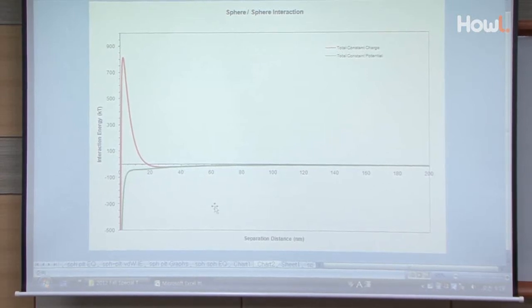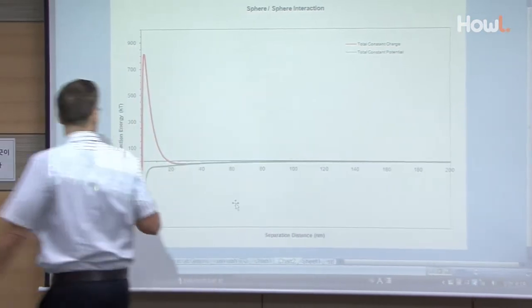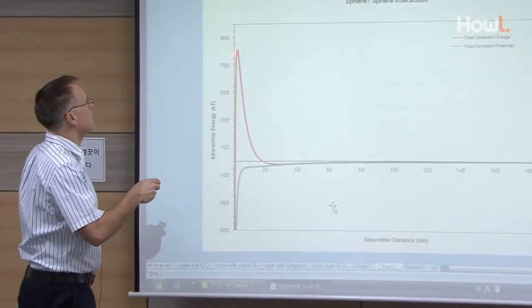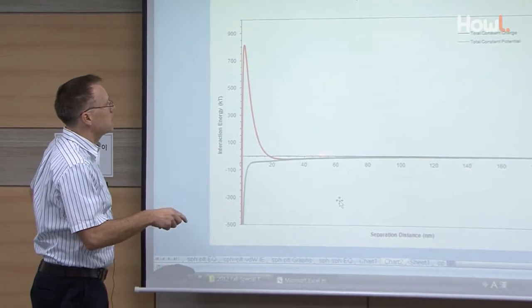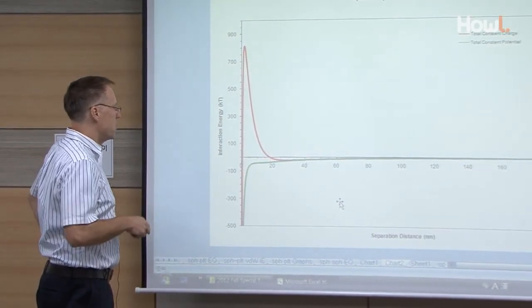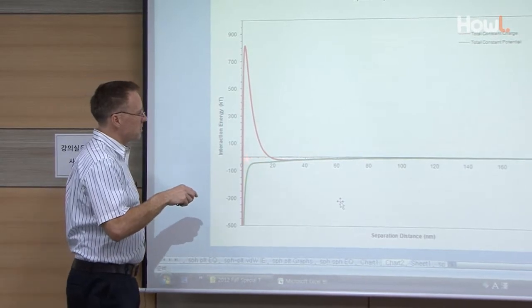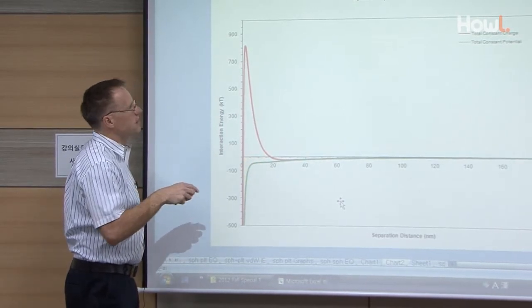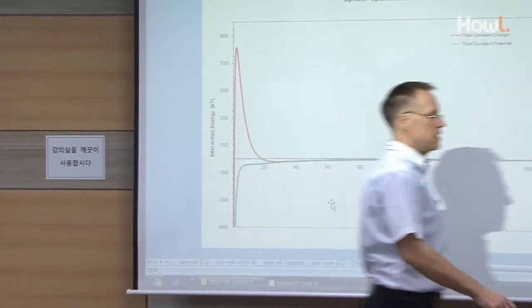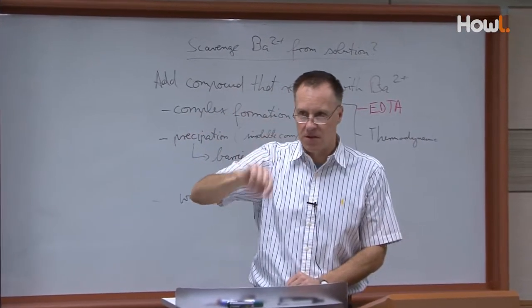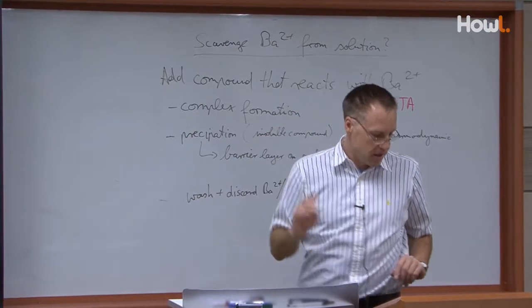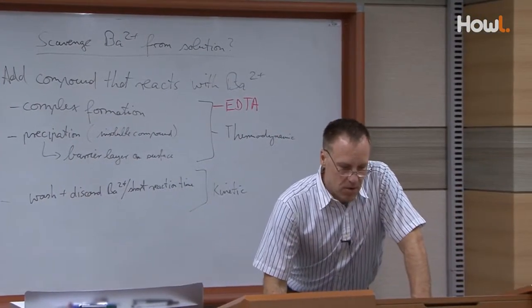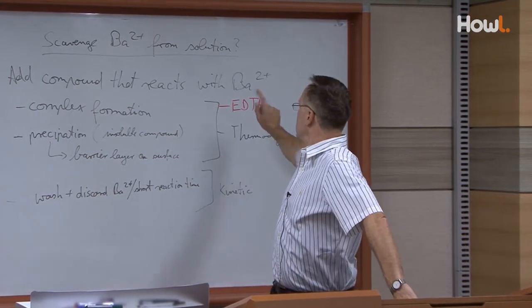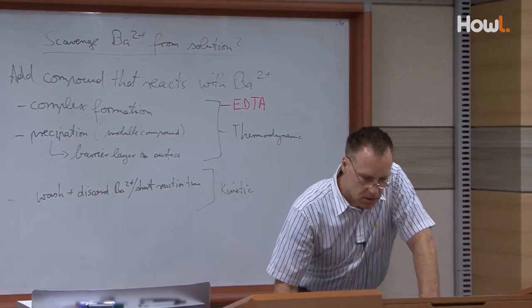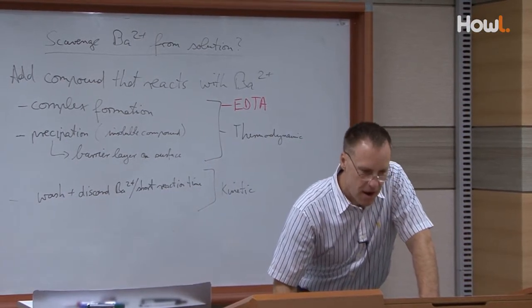As I said, you have these 2 graphs here. This is the constant charge calculation. This is the constant potential integration. And you see overall that it's most likely not to be super stable, this whole system. So at 10 to the minus 3 mole per liter of divalent ions, you basically don't have a system that is really good. And I'll show you also what it means in viscosity, because we haven't done the connection yet to viscosity. So what happens now if you put in the sodium instead of the barium at this level? Let's see whether this would work.